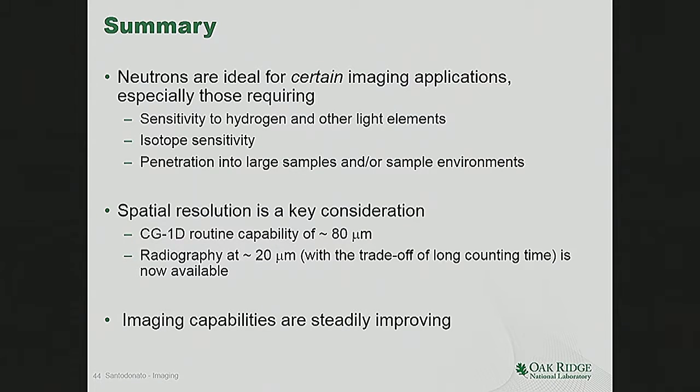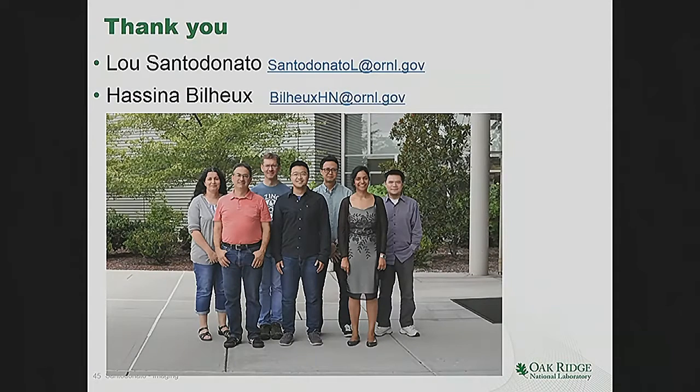Spatially, we are quite limited: 80 microns for routine work, and 20 microns we can do for radiographs that would require maybe a half hour to acquire. The capabilities are steadily improving though, so hopefully you'll see things get a lot better. And so again, there's the team, and thanks for your attention.